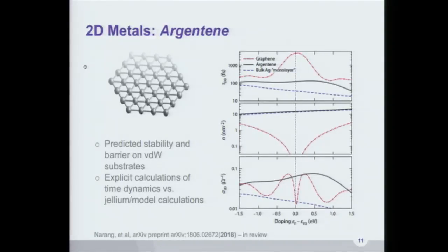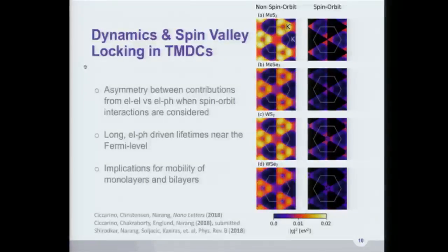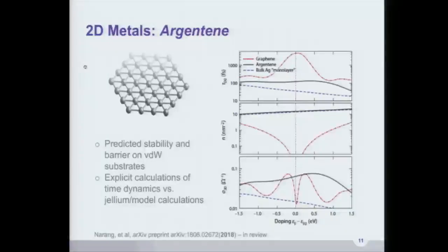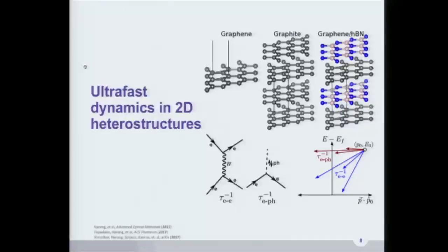And we started thinking about how we can merge our knowledge of 2D materials with our knowledge of metals to come up with a new material, a material that would fundamentally outperform existing photonic materials in the visible, okay? I say the visible because if I go back to this case of graphene and graphite, and I start doping graphene or graphene-hBN, or I start gating it, something that happens as I get further away from the Fermi level is that those lifetimes also drop very, very strongly. So that takes away from the low loss nature of graphene. The challenge was I want it to be really light, I want it to be working in the visible, and I want it to be low loss.